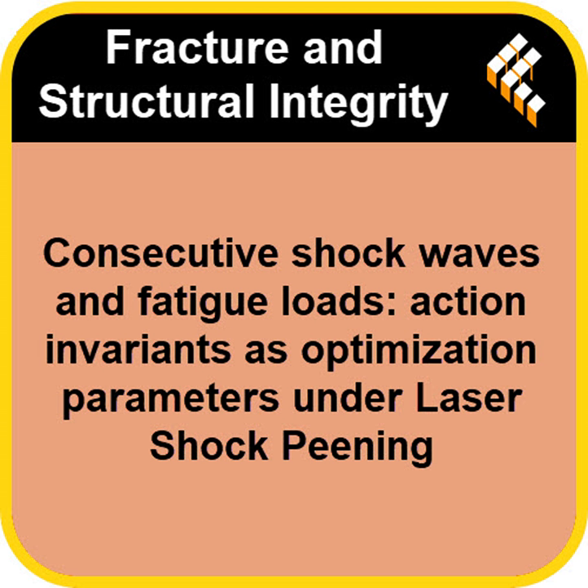but still a long test. And were they just waiting for the samples to snap? Or could they see failure coming? They monitored the internal state using ultrasonic techniques during the test. Specifically, they looked at a parameter called the nonlinearity coefficient, beta relative. Nonlinearity coefficient. What does that track? It's sensitive to the buildup of microdamage, like dislocations and microcracks. And they saw something really interesting.